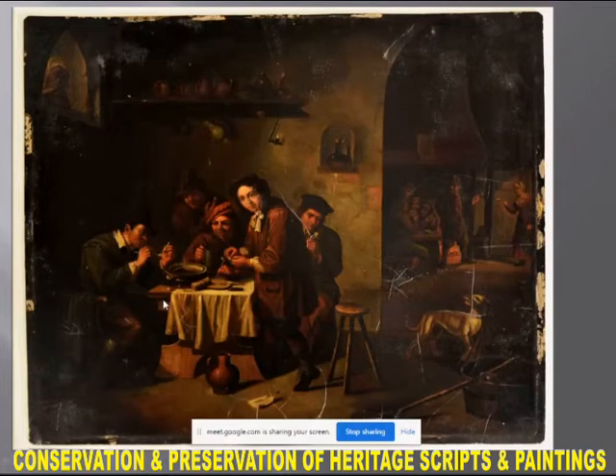This painting has varnish on top of it. It is not easy to make out in this photograph, but whenever we talk about paintings, especially oil paintings, it is important to make an assessment of whether varnish has been applied on it, because varnish will react differently. If you have not made that assessment, your treatment is going to cause more harm to the painting. Most of the time, oil paintings are relatively stable. Most of the issues they face are related to the varnish getting decayed. So that decayed varnish has to be removed, and there are multiple ways to do that.